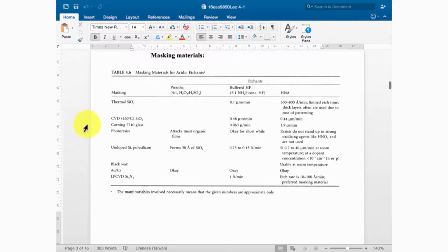Okay, so here I give you some ideas about what kind of things we can use. Actually, if you use a silicon dioxide based material, they cannot resist for a long time. So maybe for a short time it's okay, but for a long time it's really not good. And photoresist is very, very bad, actually. In this strong oxidation environment, photoresist can be peeled off quite easily in a very short time, less than 1 minute. Okay, so that's why we need a hard bake for the photoresist. Very, very hard bake. That means a very high temperature, more than 150, even 180 degrees C for photoresist.